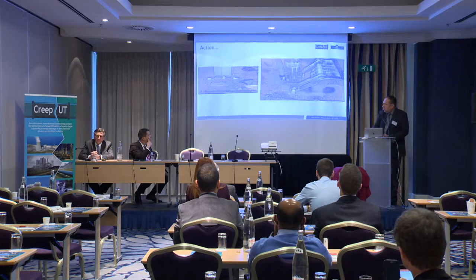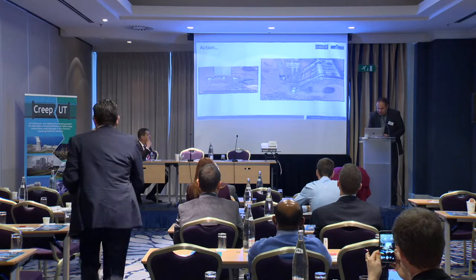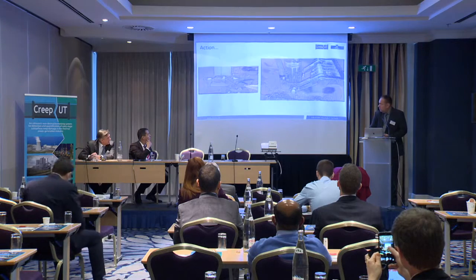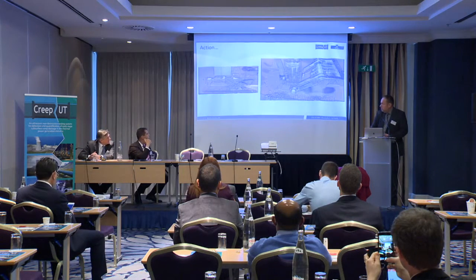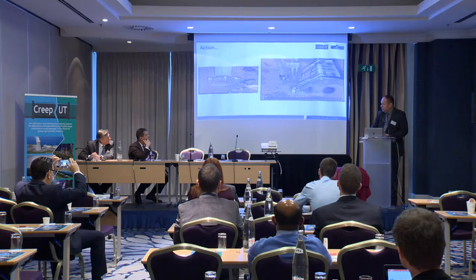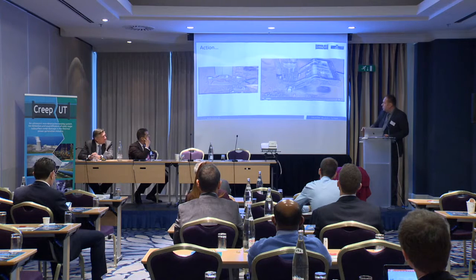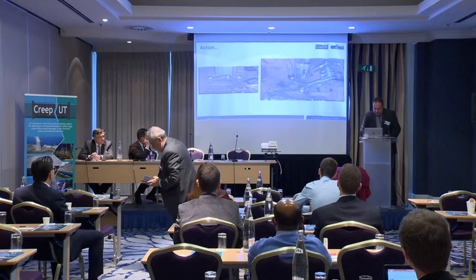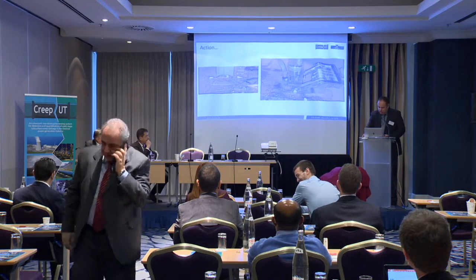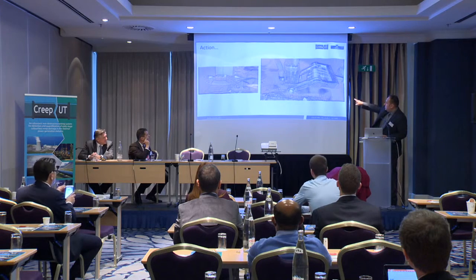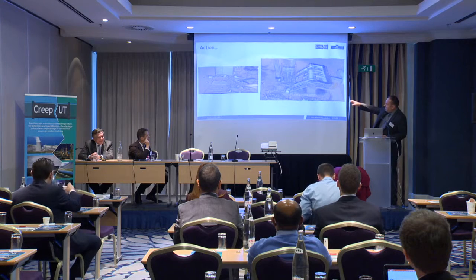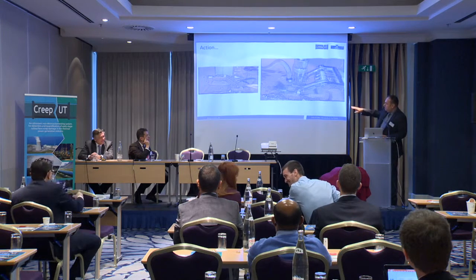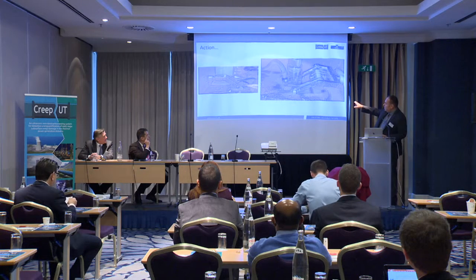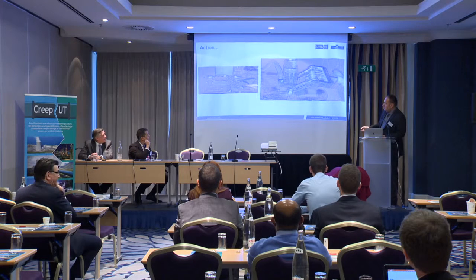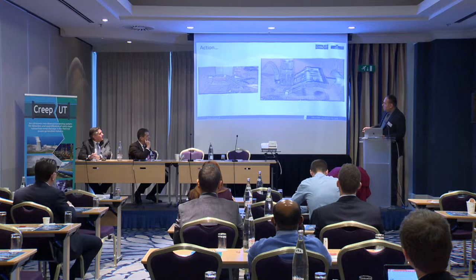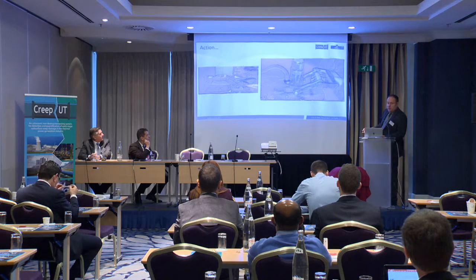Here are just some short videos of action. Maybe I should turn the sound off. This is from the lab, and this is from the plant. Just to see how it works. This is the laboratory, this is the plant, so more or less it looks the same. The pipe that we test and the weld have to be really nicely polished. There is a coupling supply, and then the only difference you can see is that this looks much cleaner than this. It's quite dirty. And here nobody was actually keen to talk in the microphone.